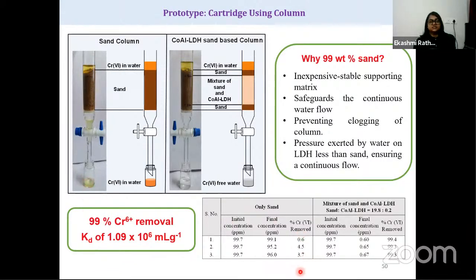And so you can see that there is such a low removal, or it's not removing at all. So here, when I mixed just 2 grams of my material with 18 grams of sand and constructed this column, we found that this yellow color is changing into white. This colorless solution is a clear indication that chromium is getting removed.